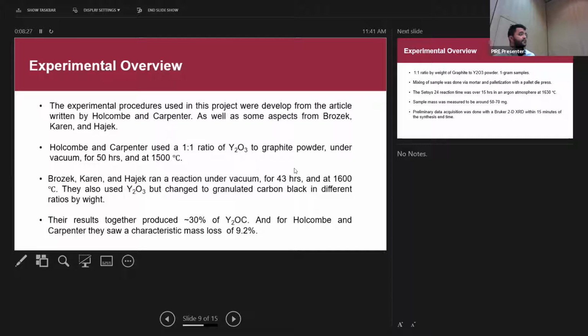They also used yttria, but changed it to granular carbon in different ratios by weight. And they actually used yttrium metal as well. So it was like a mixture between yttrium metal and yttria. And their results produced around 30% of yttrium oxycarbide phase. The other 70% is mostly yttrium carbide and derivatives of yttrium and carbon and oxygen. But that's the one that we care about right now.